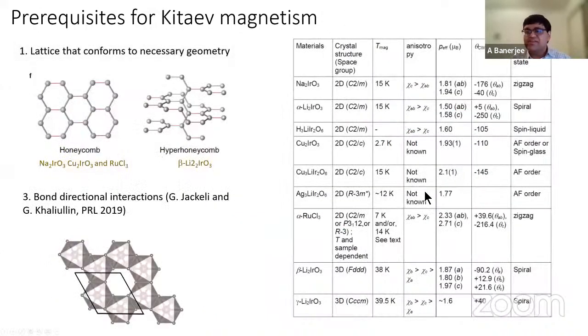So there are several material platforms where you can actually get this phenomena, and not going into the detail, people tried to make these materials for a long time. I'll tell you something, even though all these materials are made, none of these materials is a real quantum spin liquid. A graduate student or a postdoc spends 2 years to make a material in the lab, and then after so much effort, you go and start measuring it, and you see that it has ordered into some kind of a long-range ordered ground state. You don't get a spin liquid. And that's how nature behaves. Nature really wants symmetry. It wants to order in some way. It doesn't like disorder always.